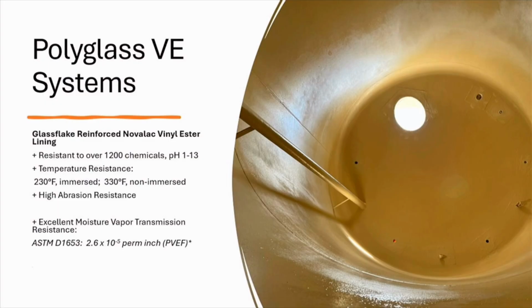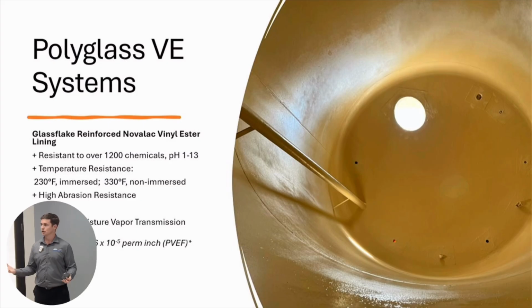I want to understand if we're going to worry about exothermic reactions that may or may not be beyond the temperature resistance of the coating. I want to understand whether or not what you're dosing in there is miscible with the solution. If it's not miscible, then you may have a hot spot. If you put 20% hydrogen peroxide into a tank, but you're only putting 1% of it, that's not a very high concentration. The coating will handle it. If it's not miscible in the tank and it falls to the bottom, now that might be beyond the chemical resistance of the coating. These little details can be the difference in a successful project or one that is a really big problem for everybody involved.